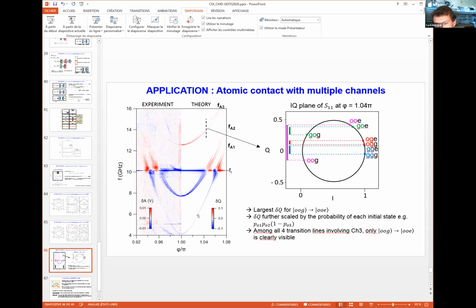So here we had 3 channels. And so, for example, on this line associated to the second channel, we do the transition from ground to excited. But then we can assume that the 2 other channels can be both in ground and excited states. So we can have 4 different occupancies, and so this gives rise to 4 different lines. So we first looked at this as an imperfection from the way we were phase biasing the weak link, but it turned out that we could reproduce this very well and extend the spectra using the theory that was developed. So this also shows you how you can really probe the microscopic occupations of the channels, which have a signature in this spectrum.